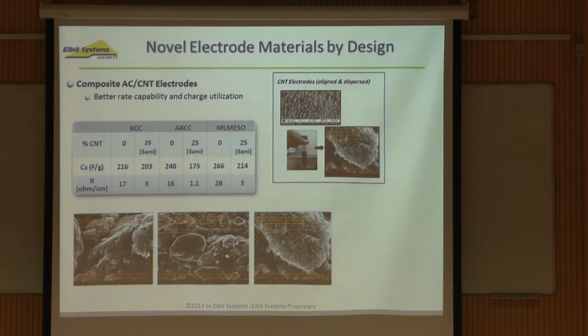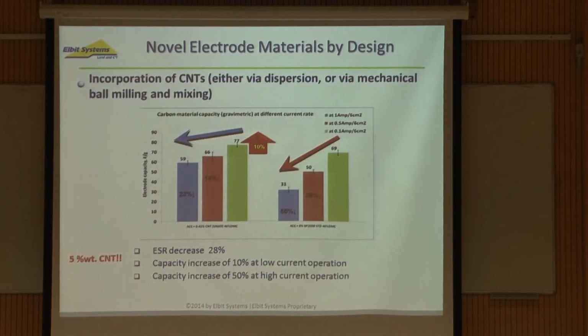And we started with very large concentrations, 25%, etc. And we found out that they had a tendency to aggregate. And then we said, okay, we will lower the concentration, because in that way we will ensure a better homogenized dispersion, and it can be done either via dispersion or via mechanical ball milling and mixing.